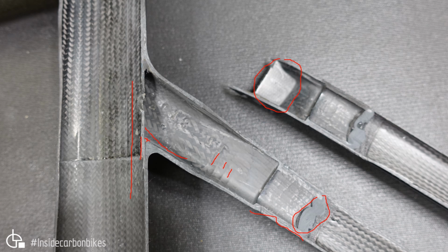Now, I'm not sure if that happened due to cutting the bike in half, because all it takes is a little bit of flex, and you can basically pop that edge open, because there isn't any fiber on it. You're relying purely on the resin for the interlaminar shear strength. And when it's a closed structure, as it would be during manufacture, it can't flex in that manner, so you can't get that sort of thing happening.